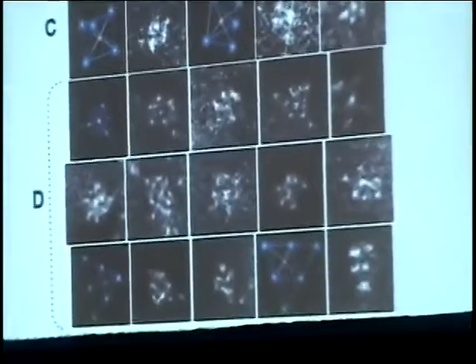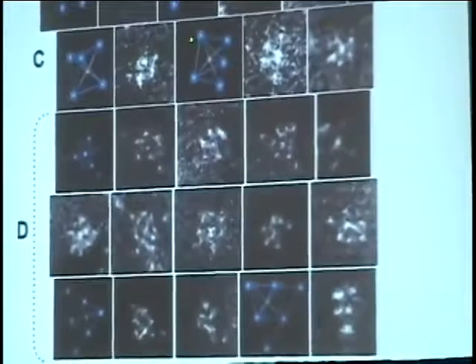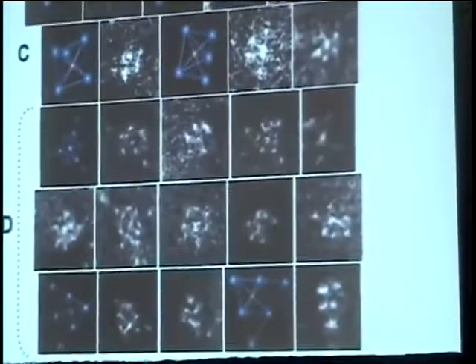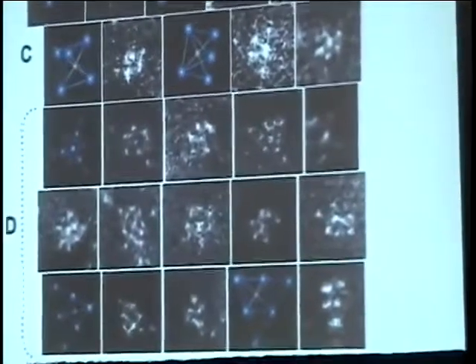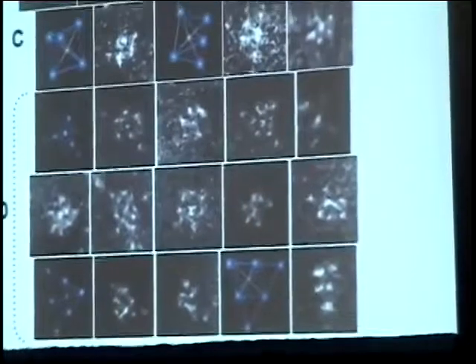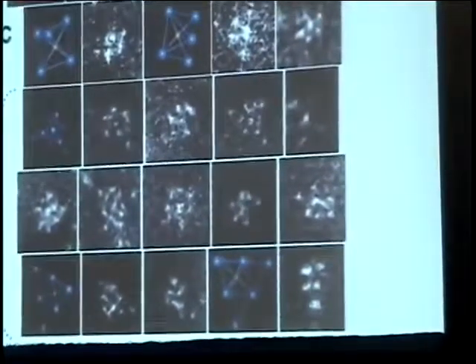So now we're really resolving 3 from 4-atom clusters. Then 5. So count them, 5. You might start disputing what I'm showing here, so I'll come to that in a minute. And then all these, category D, are the deca-osmiums, the osmium 10 clusters that I showed the structure of near the beginning of the talk.